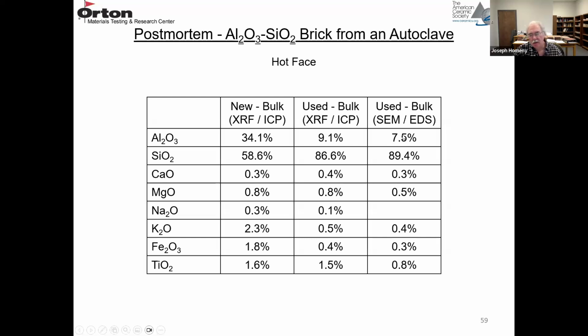And so the alumina has been attacked and removed from the process, probably an acidic process. And what's left intact is a material with a high silica content. So this is about 87%, this is about 89%. So whatever process they were using to extract the metal, the MO metal, was probably an acid-based process. Silica is an acid refractory, it's resistant to acids. So it was not attacked, but the alumina is more neutral, it's neither acidic nor basic, so it was attacked first.